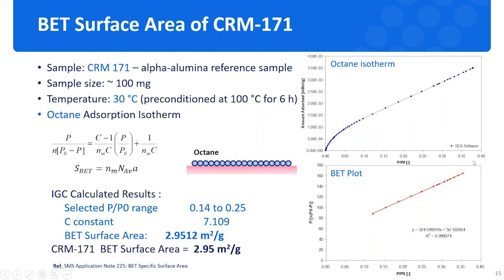And from the slope of the BET plot and also the intercept, we can then get the sorption constant and the monolayer volume. And we already know the cross-sectional area of the octane molecules, then we can get the surface area of the material. So the reported value for this CRM171 sample is about 2.95, and we get highly consistent BET surface area with the IGC technique. So this is the experiment for this reference material at room temperature and also 0% humidity, which is an ideal condition that in the real world is without any humidity at all.